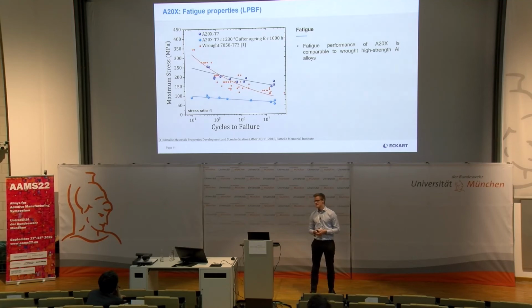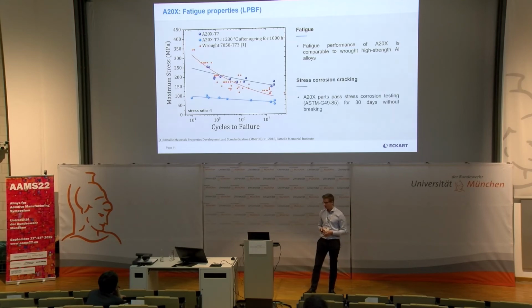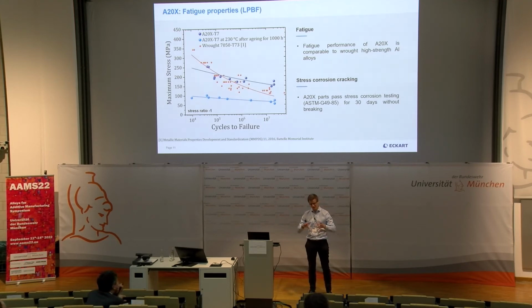aerospace applications. Now, on the note of severe testing conditions, many aluminium copper alloys are prone to stress corrosion cracking, which is a form of corrosion that is made significantly worse when stressing the component. Standard stress corrosion cracking tests involve keeping the test piece in a stress condition up to 80% of the yield stress in a 3% sodium chloride salt mist chamber for prolonged periods of time. And what we see is that A20X samples pass standard stress corrosion cracking tests for 30 days without failure.